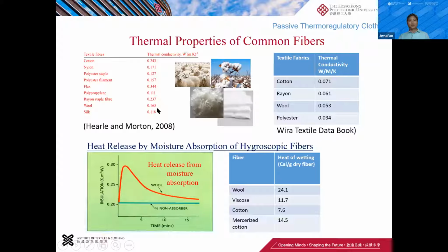Right? Now, in terms of fibers, the thermal conductivity could range from like 0.11 up to like 0.3, like flax, a little bit cooler. But to us, this is not significant at all, because in a piece of fabric we wear, typically 80% is pores. There's 80% porosity, pores inside. Only 20% are fibers. Now, when we talk about insulative material like down or Thinsulate, the porosity could be 99%, and only 1% is fiber. So whatever fiber you have, in terms of this kind of protective garment, that really doesn't count for much.